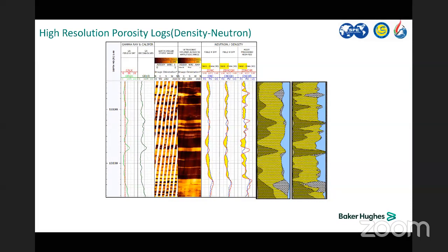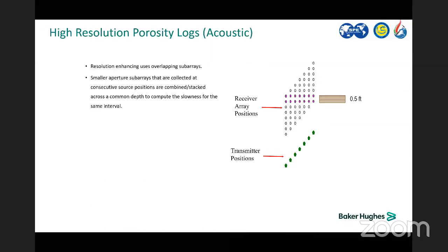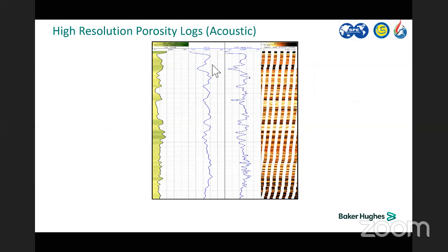The same here in acoustic, or Baker Hughes calls it acoustic. Maybe you are familiar with sonic. You are able to get a high resolution of up to 6-inch, half foot, vertical resolution for the acoustic. You can see the track on the left is the conventional one which you receive every day, and the right one is the high resolution 6-inch. You can compare both of them to the resistivity image. You can see the difference and the impact in your multi-min analysis or in your shaly sand evaluation model.